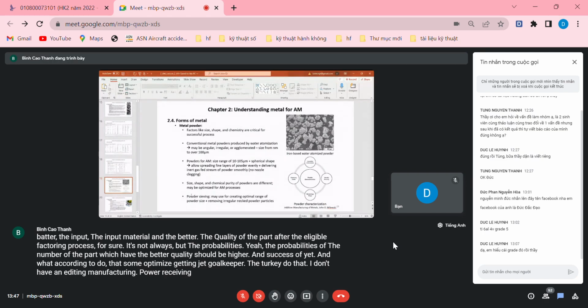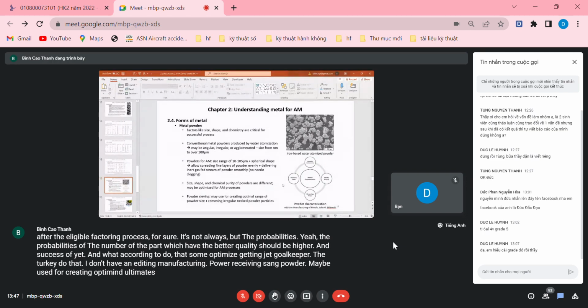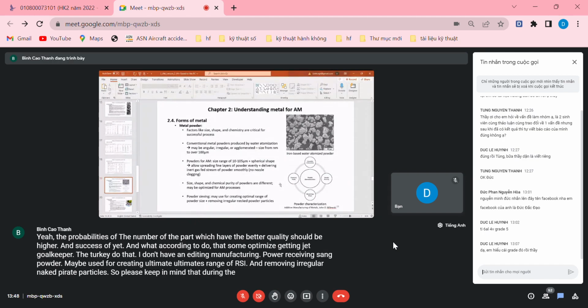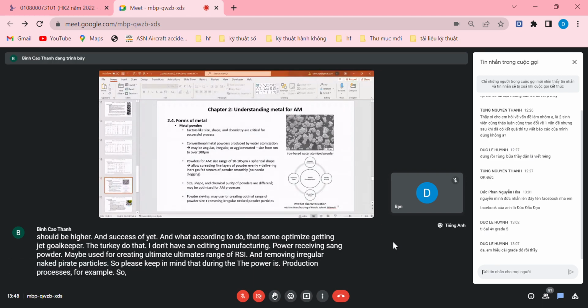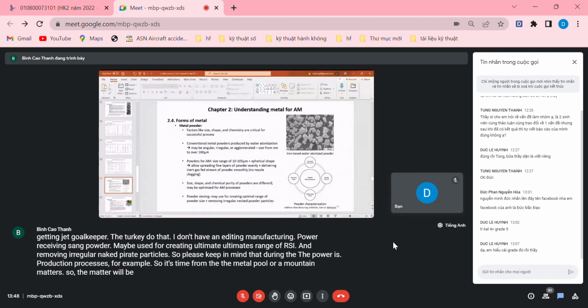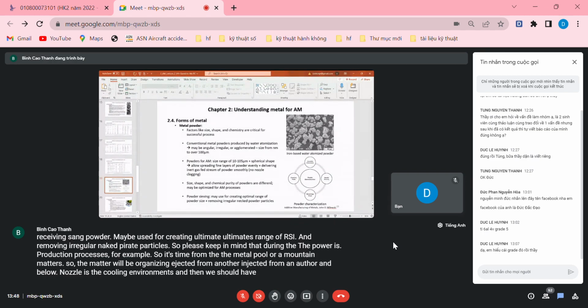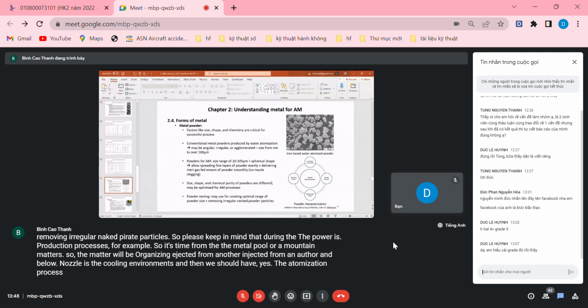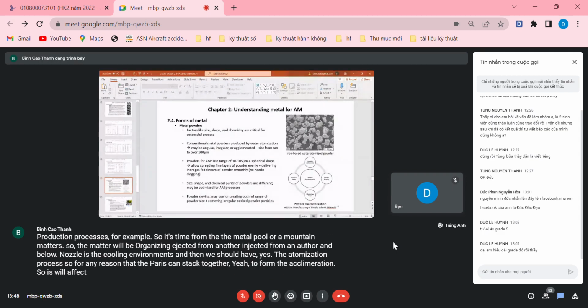Powder sieving, which means sieving the powder, may be used for creating an optimal range of powder size and removing irregular shaped powder particles. So please keep in mind that during the powder production process, it starts from the metal pool or molten metal. The metal will be ejected from a nozzle, and below the nozzle is a cooling environment, and then we have the atomization process. For any reason, the powders can stick together to form agglomerations. It will affect the spreading process to create the layers for the powder bed fusion process.